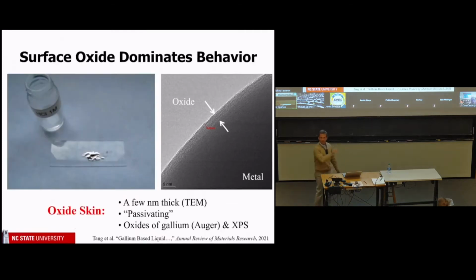So this is the most important slide, so take your eyes off your cell phone for a second. This is the metal spread out on the glass slide, and if you dip this Q-tip into this vial, you'll get a little bit of acid on it, and that vapor from that acid dissolves off that oxide layer. So this is kind of the punchline of a lot of things I'm going to show you. In air, it forms this oxide. It's like a waterbed. It forms a skin, but we can dissolve it off using acid.